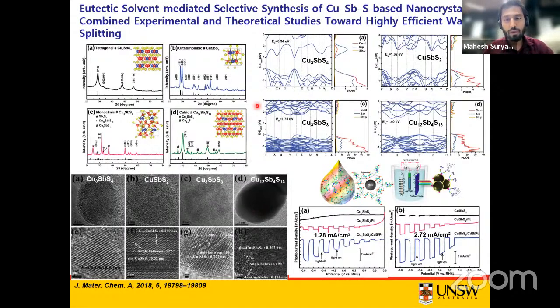So in this case, what we have done is we made thin films from nanocrystal ink of these nanocrystals, and then we prepared thin films, and we use these thin films as a photocathode instead of a photoanode for water splitting reactions. So if you see these 2 plots, you will clearly see that.